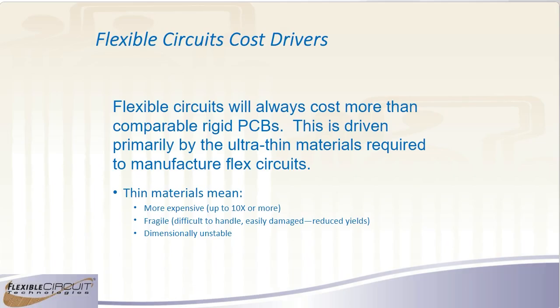Probably a bigger thing up and beyond just the raw material cost, though, is that they're fragile. They're so easy to damage. If you take a large sheet of material and you pick it up off the table from a corner, you can damage it just because you can get a ripple that'll run across the copper, and it's almost impossible to get that area to not etch out when you're doing your photo etch process. So that's a concern, and it's also dimensionally unstable. And I'll go through some of the problems with that later in this presentation.